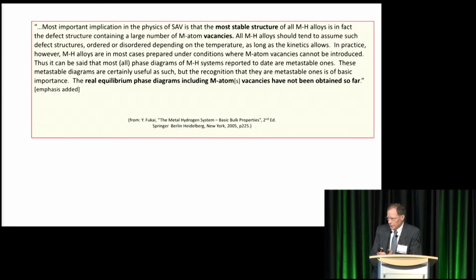So the thermodynamics is going to tell us they should be there. Whether we can get there or not depends upon the kinetics. In practice, however, metal hydrogen alloys are in most cases prepared under conditions where metal atom vacancies cannot be introduced. So we're going to have a problem with some of the kinetics. Thus, it can be said that all phase diagrams of metal hydrogen systems reported to date are metastable ones. These metastable diagrams are certainly useful as such, but the recognition that they are metastable ones is of basic importance. The real equilibrium phase diagrams, including metal atom vacancies, have not been obtained so far, maybe until today.